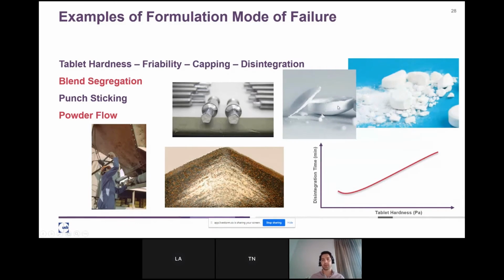You also have capping, where due to the level of hardness, or also the plasticity or elasticity of the particles, you might form a cap, which is undesirable. Also, on disintegration, we could sometimes have a problem where we increase the hardness too much. We know there is a correlation between the disintegration time and the tablet hardness, and that would be undesirable, because we need a specific range of values for disintegration time to let the tablet disintegrate, and then later dissolve and be absorbed by the patient.